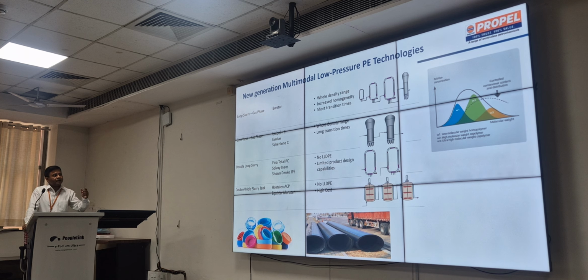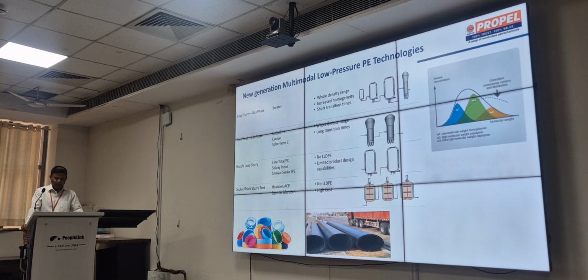This multimodal just explains the Borstar. Borealis is very strong in the technology, and that's why their grade basket is much superior to any licensor. And there is not much data available about how they are producing. You can get the reactor system, but still there is much less information available for such technologies. You can use a loop reactor system, single or two loop reactors or three loop reactors with fluidized bed reactors. In the case of Unipol or Spherilene, two gas phase reactors can be used. In the Hostalen ACP, three different kinds of reactors. In each reactor, different reactions happen, and the output of one reactor is the input of other reactors. So different molecular weight fractions can be produced.